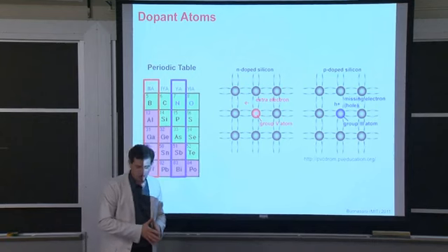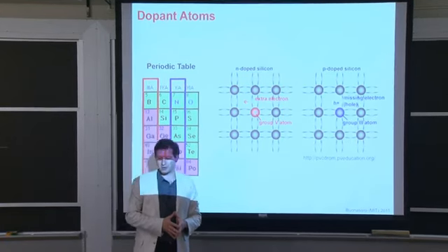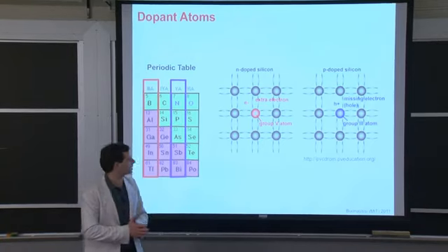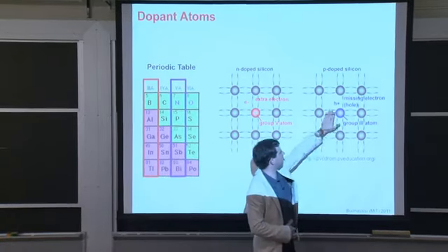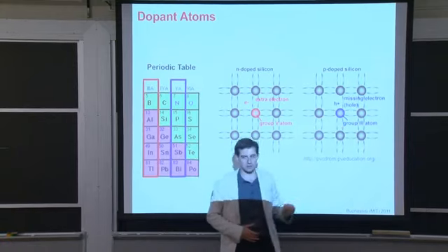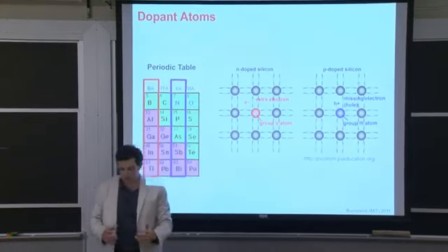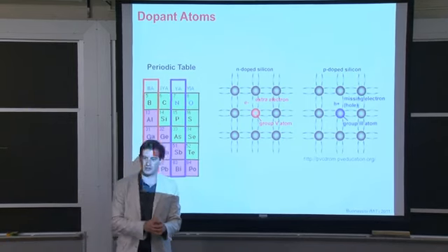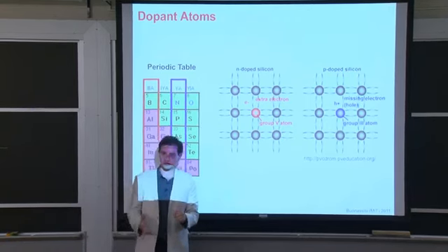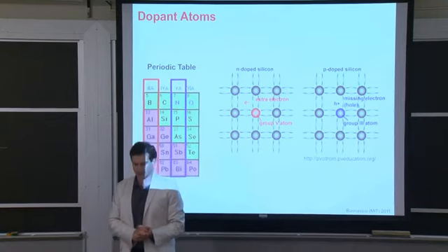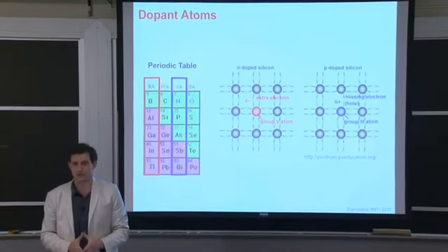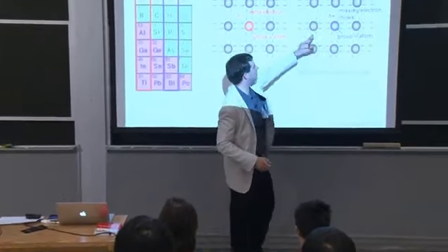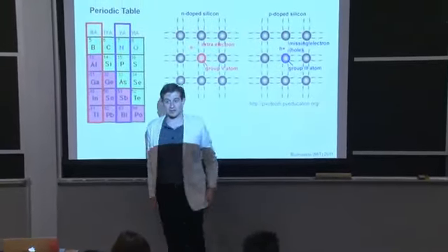Another way that we have very strong evidence that boron is occupying a substitutional site and not an interstitial site is we can calculate the binding energy of this hole to the boron atom here on the substitutional site. In principle, if the interstitial was a charged defect, we could calculate the binding energy of the charge to that defect. And density functional theory could tell you which is the more likely, given your experimental observation that you get about one hole for every one boron atom inside of your sample.